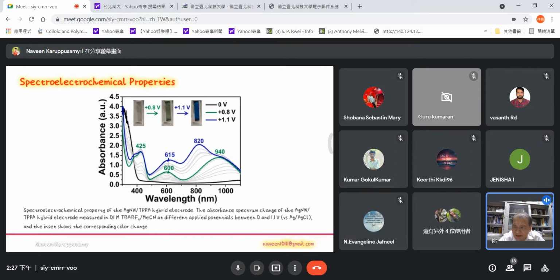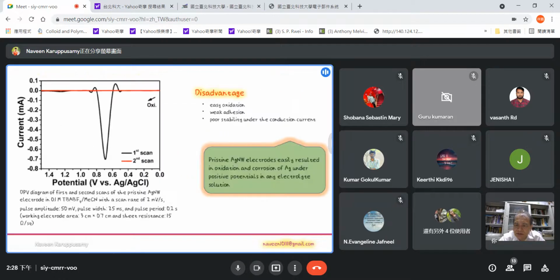So what does TPPA mean? Triphenyl polyamine, Professor. What kind of material does it act as? Is it a sensor for the metal? No, it's not a sensor, Professor. They use the passivation layer to enhance the stability of the silver nanowire. Instead of performing with only the silver nanowire, in the very second performance no oxidation peak is observed, Professor.